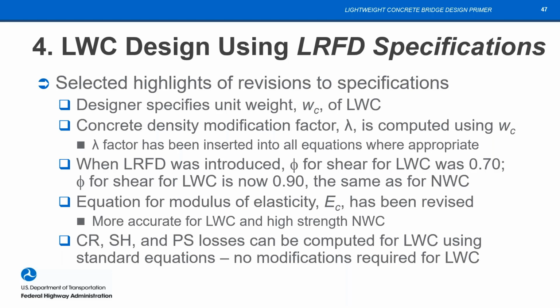Another thing is that the resistance factor for shear used to be 0.7, where it was 0.9 for normal weight concrete, and now the shear resistance factor for lightweight is equal to that for normal weight at 0.9. There was a new modulus of elasticity equation, and then creep and shrinkage, pre-stress losses. It's been found by research that we can use the exact same values, equations that is, that are computed using the standard equations without modification when we're designing for lightweight concrete.